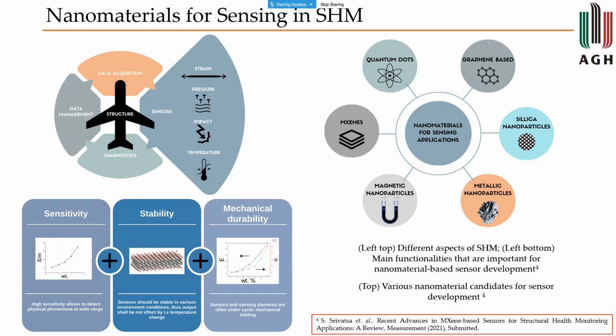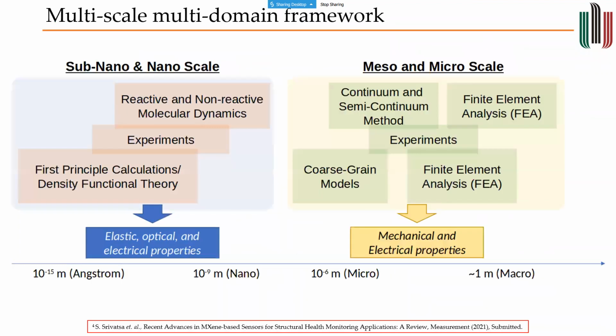So these are some of the aspects that we dwelt on before we could get into the fine details of the work. We started off building numerical models first before we could do some experiments. The time of synthesis and processing these materials took considerable time, which also gave us some time for numerical modeling. Most of the properties at sub-micron scale were being reported by 2018, and we had enough input from the literature that could be used to build models from micro to macro scale. And the initial choice of methods of modeling from micro to macro scale was very standard and also being used for other nanomaterials.